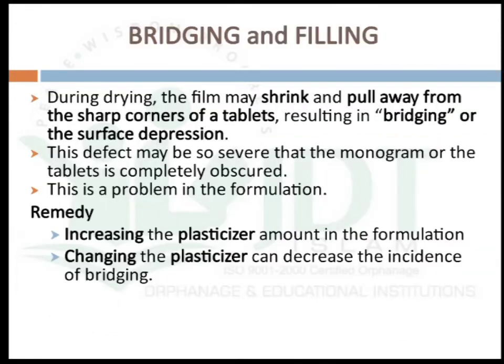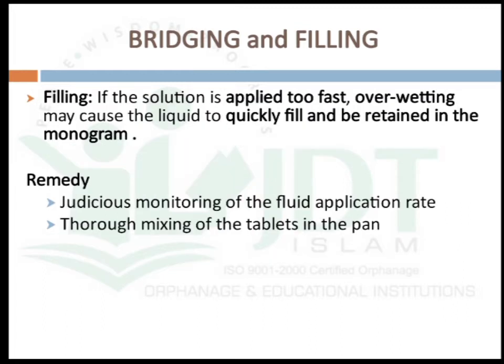The next defect is bridging and filling. During drying, the film may shrink and pull away from the sharp corners of the tablet, resulting in bridging or surface depression. This defect may be so severe that the monogram on the tablet is completely obscured. This is a formulation-related problem and can be rectified by increasing the plasticizer amount or by changing the plasticizer.